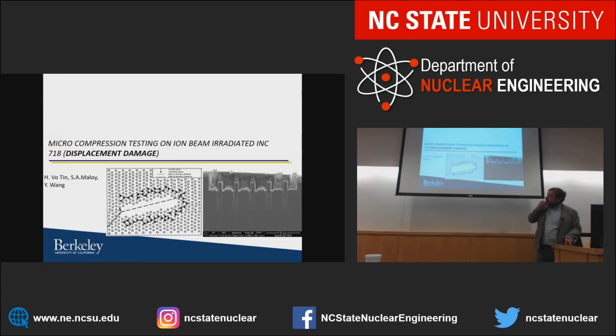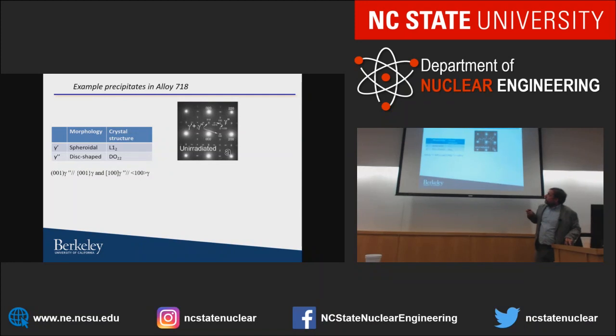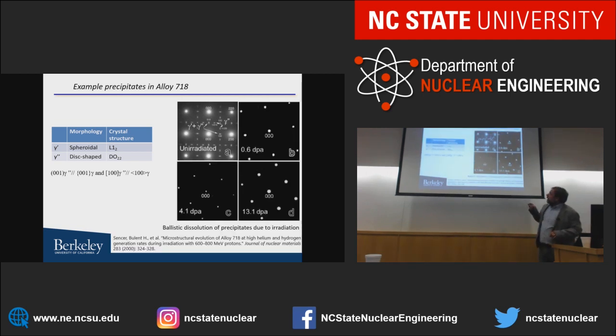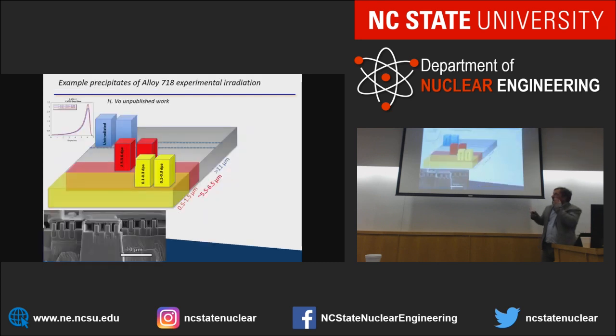Another similar example is on alloy 718, which has now been irradiated, and it's well known that 718 forms gamma double prime precipitates, which are the strengthening features. They give us the strength of this material. Well, it turns out that if you radiate these materials, these gamma double prime features go away. They dissolve. You shoot them back in solution. So that's not new. But we can now use ion beam radiation with this small-scale mechanical testing to look at these precipitates getting dissolved or not dissolved. So we do an ion beam radiation into material, similar to earlier, low dose in the front of the peak, somewhat medium dose here, and then unirradiated.